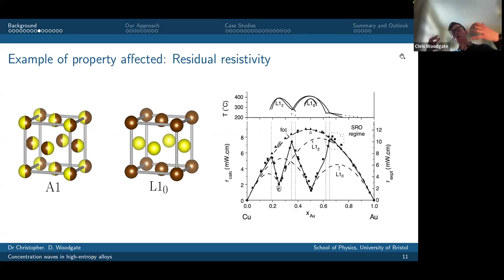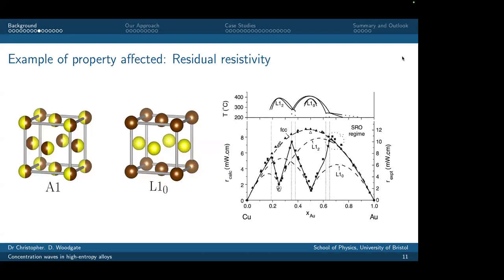What happens is you don't quite have a completely disordered system that immediately goes to a perfectly ordered system. What actually happens is as you approach these transition temperatures, as you approach the L10 transition temperature, what you find is that locally certain atoms prefer or dislike certain pairs of atoms nearby. So there is a finite region about the ordered phases, between the melting temperature and the order.